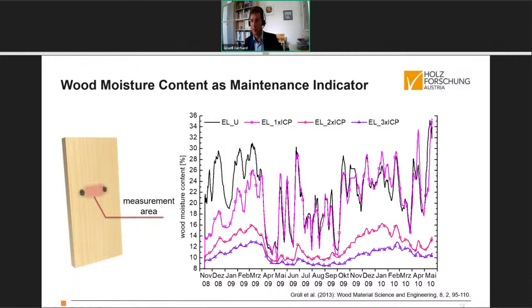These are three different coating systems. The product is called ICP, which some of you may know from the old standard EN 927 Part 3. This was put on the wood surface with 1 time brushing, 2 times and 3 times brush application. And you see the moisture fluctuations of uncoated wood in the black curve. So moisture fluctuates really a lot. It dries down over springtime here and is a little bit lower in summer and has very high fluctuations.